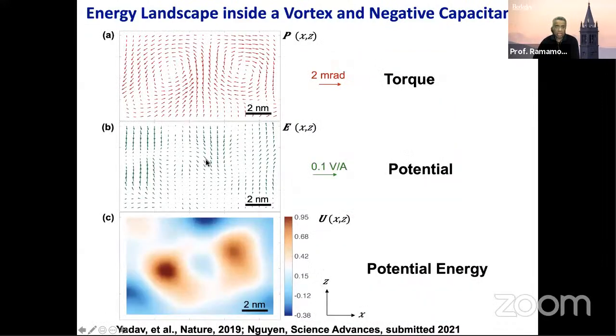So what we did was we took this electron beam. We could measure the torque on the beam, which is coming from the angular momentum. We could also measure the spatially resolved potential of this with the holographic type measurement, and you can convolve the two of them to map out the potential energy.